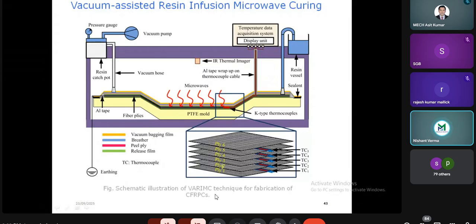damage, in order to make the composite. It is not recommended, or it is less recommended, to use the direct pressure in case of thermosetting matrix. So how have we made the arrangement of this in case of microwave? What we have done, on one side we have taken a vacuum pump in order to make the vacuum pressure, and some laminates are there, fiber laminates, and after